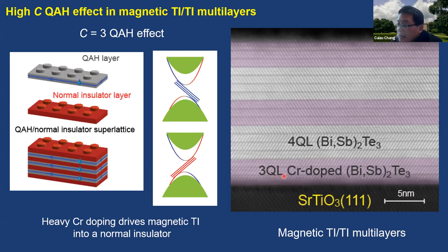This is a three quintuple layer heavily chromium doped bismuth antimony telluride. This is the undoped TI layer. And as I told you, heavily chromium doped, this will become a normal insulator. And just because of the proximity effect, it can drive the undoped TI layer here to become a quantum anomalous Hall insulator layer. So the total Chern number in this kind of layer is just determined by how many undoped TI layers are in the multilayer samples.